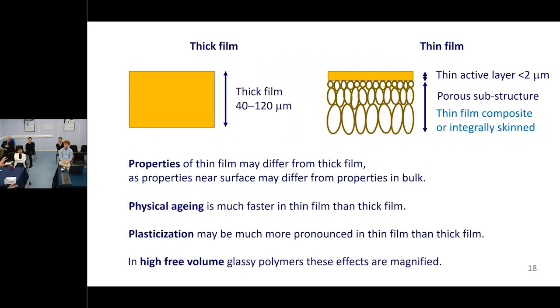So, when you're at university, you do things for publications, and there's lots of literature on membranes, gas separation membranes, pervaporation membranes, where we're studying these thick films, which might be 40 to 120 microns in thickness, in order to understand how a particular polymer or particular material behaves. But the problem we have is that when we try to go to a real membrane, we're now going to something which is very, very much thinner.